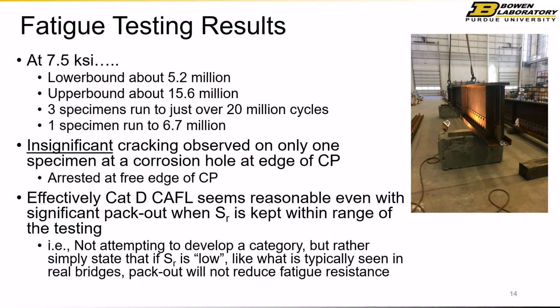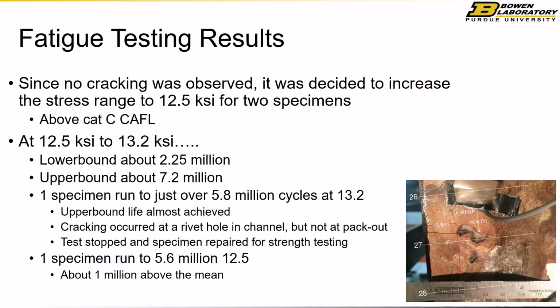Now, there were a couple cracks that appeared at other rivet holes, like in the sides, where there was no real pack out or anything, and it should crack, right? It's well beyond the lower bound. But in the regions of the pack out, there was no negative impact of the pack out. So, Category D, which is what you could use for evaluation, still seems to be reasonable when you have significant pack out.